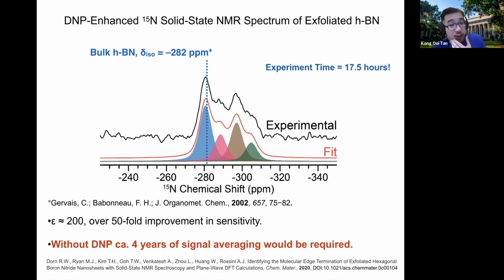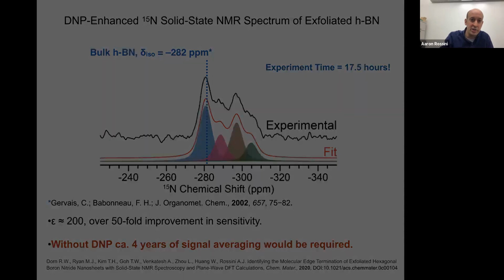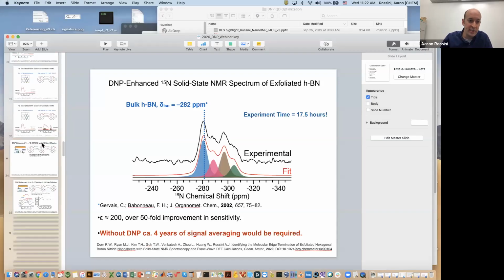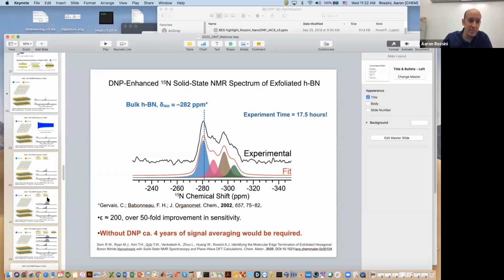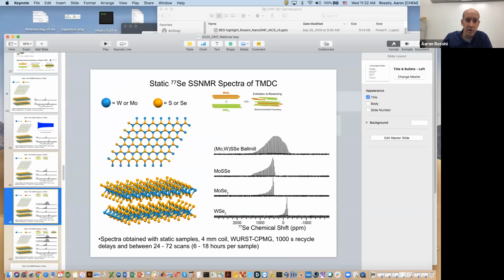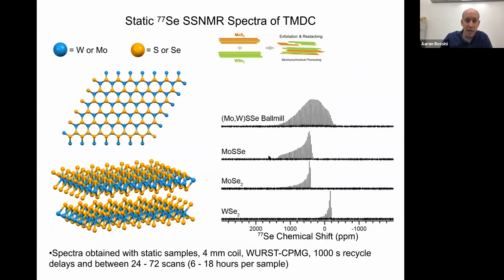Have you estimated the spin diffusion rate between the selenium? Selenium, no, we haven't tried to estimate that yet. I think that's one of the issues that also prevents DNP from working in the mixed systems. DNP probably works fairly well when you have the pure selenides, because each of those selenium atoms that make up the material is going to have the same chemical shift.